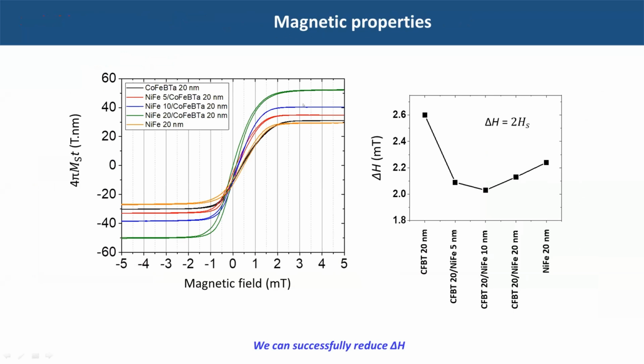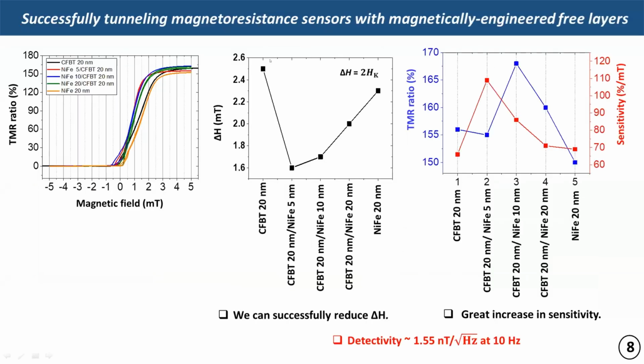this is the result of the magnetic properties from the thin film, a very linear curve, as you can see. And as you can see here, we can successfully reduce delta H. This is from the magnetic thin film. We got the same result from the TMR curve after microfabricated devices. And the same, actually, we successfully reduced delta H. And because of this, we can successfully double or increase sensor sensitivity from 70% per millitesla to over 110% per millitesla. And so the detectivity improved to 1.5 nanotesla per root hertz.